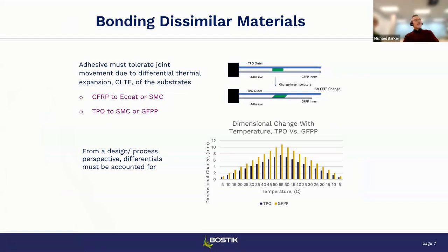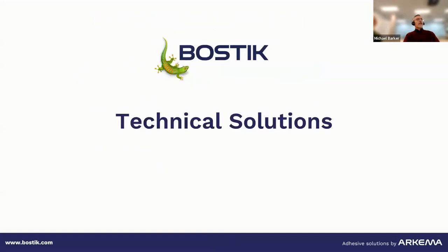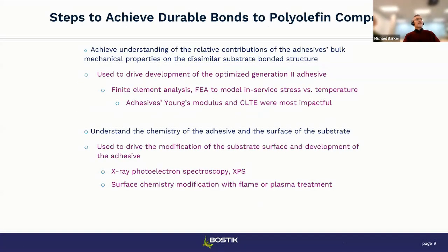When the temperature changes, and we can use an example of having cool temperatures in the morning and higher temperatures in the midday, and then cooling down again in the evening, the two substrates will expand and contract at different rates. And that puts a lot of stress on the adhesive. And that's really what we're going to focus on today, is how do we deal with that stress, number one, and then number two, how are we going to get the adhesive to bond to a polyolefin, which is a very hydrophobic type of substrate. So those are our objectives, and these are our solutions.